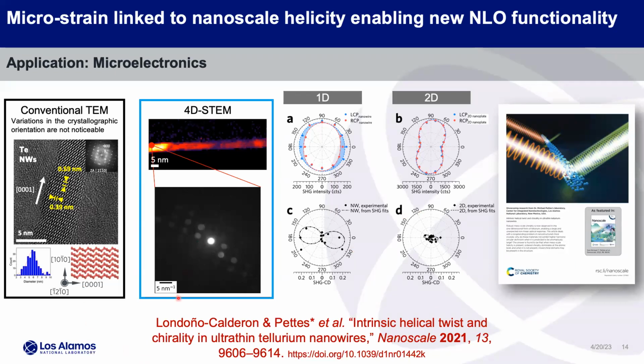But you can see, that doesn't let me click on it. But if we scan across this, you would see the diffraction pattern change. The real breakthrough that we had was that all of the talk on circular polarization in chiral crystals for tellurium wasn't measured, but we measured it with a nanowire. And then because we have these electron diffraction techniques to look at longer range helicity, which we measured to be about 50 nanometers, we picked up certain